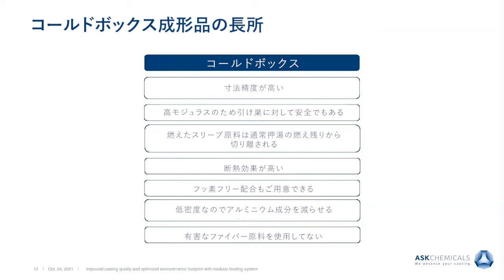The advantage is also because of this mixture of the exothermic and insulating ingredients like the microspheres, that they can also be used safely for high moduluses, means moduluses bigger than 5 centimeters, where are the natural limits of the inorganic ones.